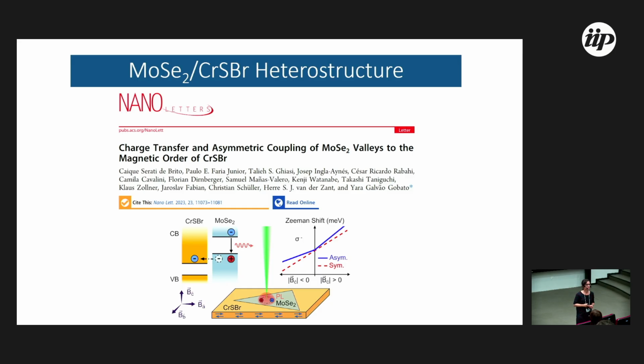Okay, and the second quick question regards the coupling mechanism between magnon and exciton. Is it just a simple magnetoelastic coupling? I don't know the models that they use. There's some experimental evidence, because they show that they can see the frequency of the magnon and they test several measurements to prove that it was magnon and exciton. But it's not my work. I looked at the paper. They prove it, and there is not only this paper. There are others. They apply strain and they check everything that proves the exciton coupling. But the mechanism I don't know. Okay, thank you.